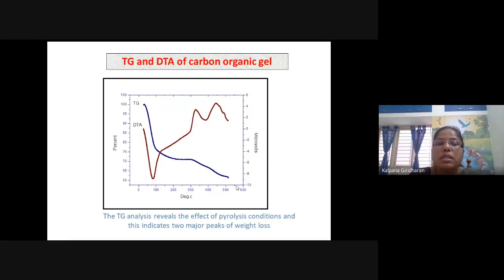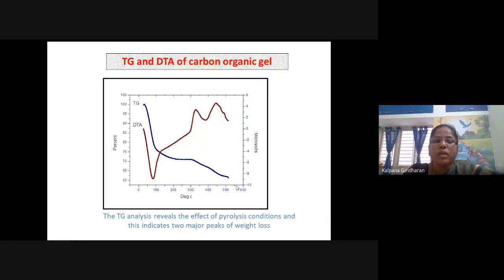This is a typical TGA, thermal gravimetric analysis. At around 100 degrees Celsius, the water will go out, and then we could see the effect of pyrolysis conditions because of this weight loss.